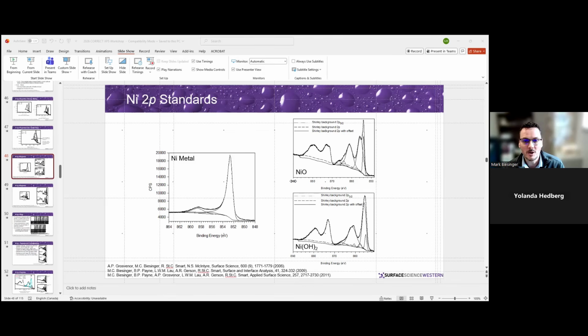What are the best ways to determine correct RSFs, and when is it fair to use the CASA default ones? If you don't have any other choice, the CASA default ones will work and will give you reasonable results. If you can get the correct relative sensitivity factors that match your instrument, that's probably more appropriate. For example, we have Kratos instruments here, and we're able to get the correct relative sensitivity factor table and use that in CasaXPS instead of the standard ones. That being said, a Scofield table of RSFs works pretty reasonably, as long as you're not jumping between different RSF tables while you're trying to compare materials. That would be a problem.